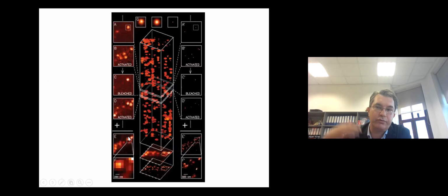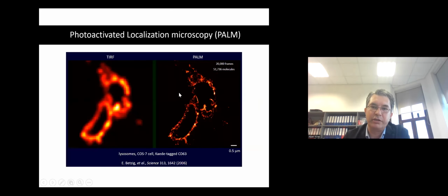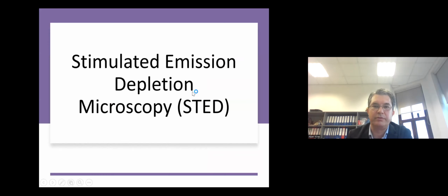It requires a lot of consecutive images to be collected. In the first demonstration, I think it took like 1 day to record all these images, localize the molecules, and reconstruct the whole image. But at the end, if you do this patiently, you get a much more improved image. So you can go down to 20, 30 nanometers in resolution with the PALM technique.